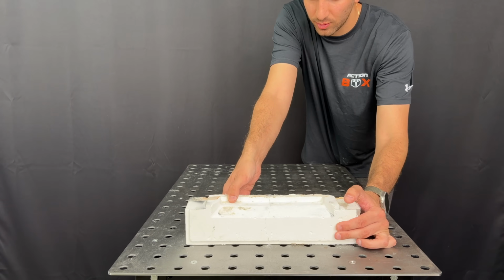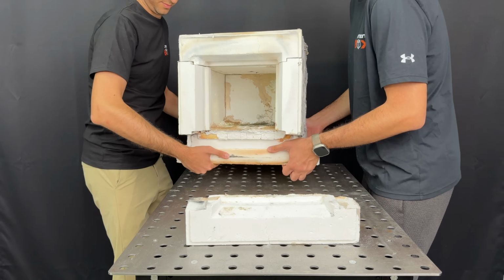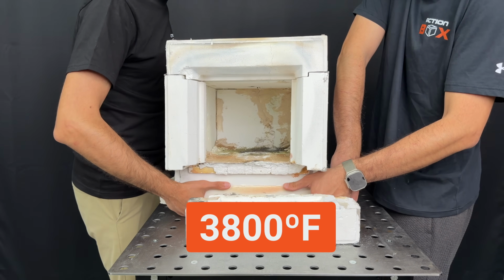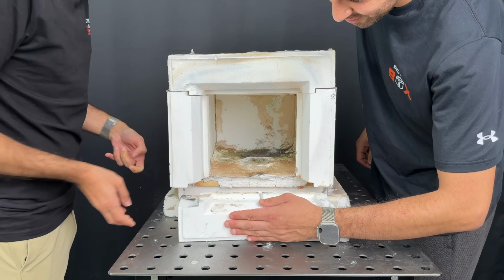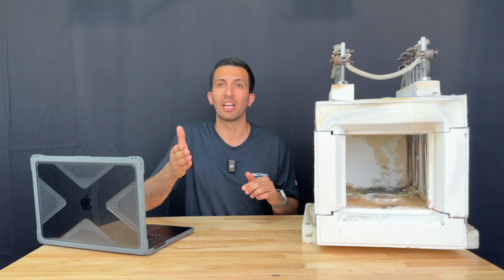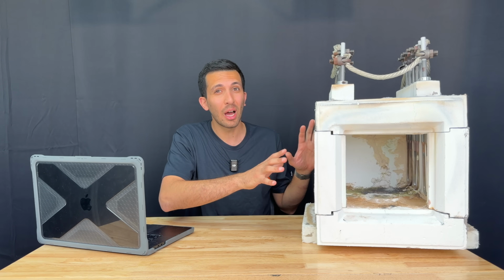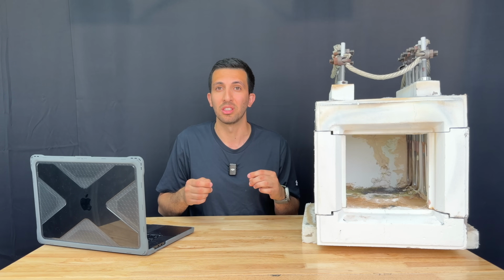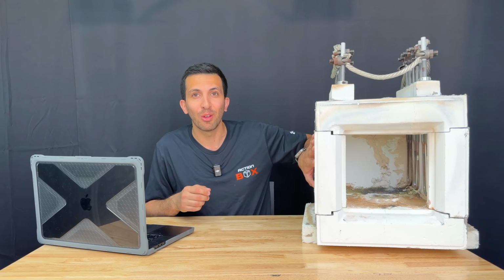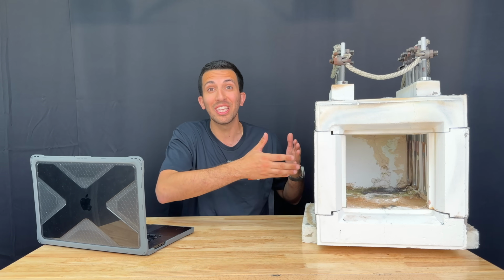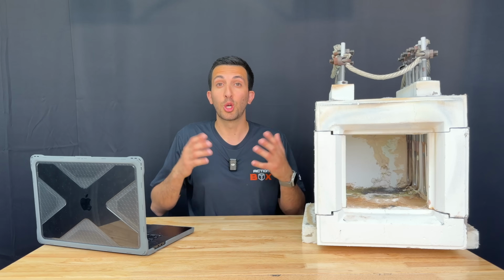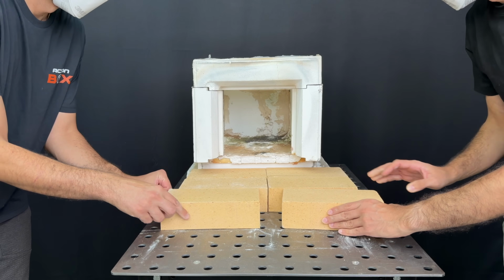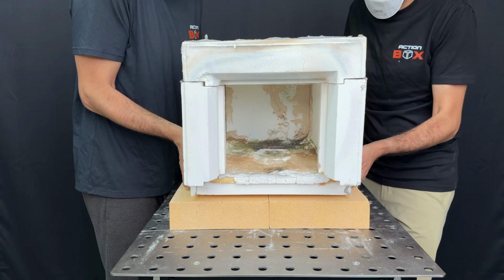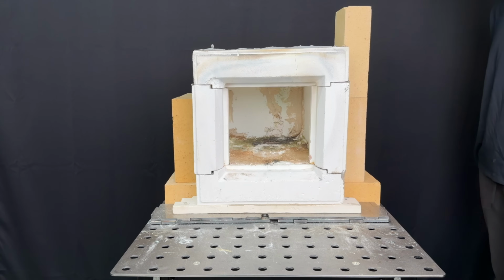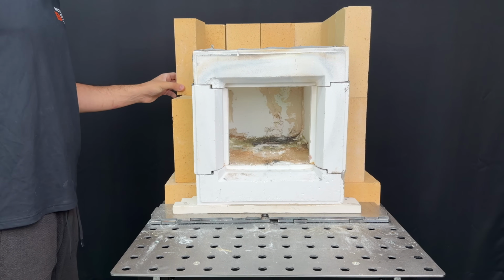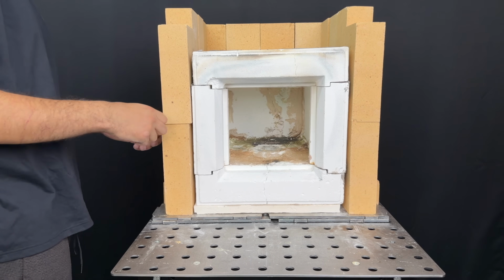Instead, I went out and got aluminum oxide blocks, which not only survive upwards of 3800 degrees Fahrenheit, but also insulate extremely well. Now you can see that I already tried to assemble a furnace, but when I fired it up, it wouldn't go over 2600. Why? Well, when you touch the outside of your furnace, it gets very hot, so clearly heat is lost to the environment. To combat this, I have to add another layer of fire brick to help trap the heat inside. These are only rated to 3200 F, which is fine because they're not directly exposed to the heat. I chose this because it's much cheaper than alumina.